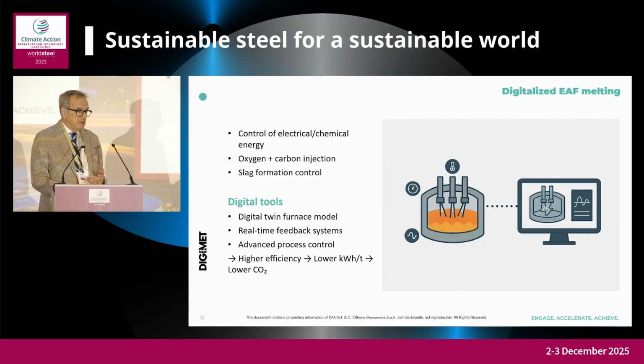If we are talking about DANIELI Automation, some of you already know the use of Melt Model, which is based on this concept. This ensures optimal energy use and improved slag forming, leading to better heat transfer. Slag forming, of course, is one of the most important, critical portions of the process of transformation inside the electric furnace. Having the perfect composition of the charging, the models can also predict much better the slag forming.